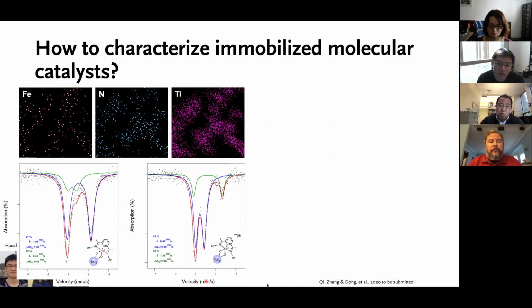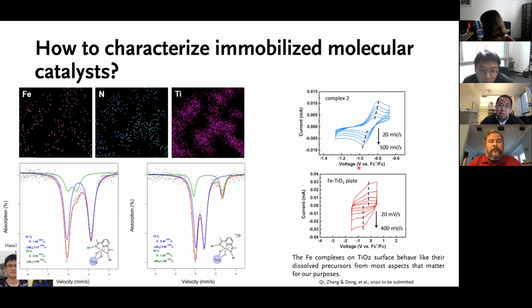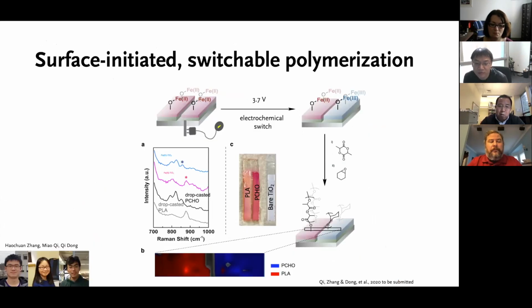But the real powerful information comes from Mössbauer spectroscopy. We benefited from the Mössbauer spectrometer at Harvard, Ted Betley group. And what's really important, the key take-home message without going into the details here, is that the spectroscopic features of both the iron 2 and iron 3 complexes are very similar to the dissolved iron complexes in the solution. So we have confidence that we now have a complex that can give us the desired switch behavior as well as the polymerization results. So I'll show you on the next slide how the polymerization worked out.